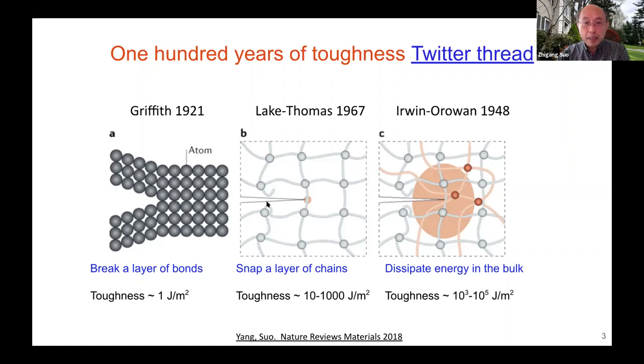When this chain breaks, it only breaks at a single atomic bond, but the entire chain's energy is released because of stress deconcentration. In this case, the stress is deconcentrated from a single bond to the entire chain, maybe even a few neighboring chains. This process is not available in glass. So as a result, you have to snap a layer of chains, not a single bond anymore. You only break one bond, but you dissipate energy in the entire layer. So the toughness is immediately amplified by the number of bonds, right? So you can see why this is important.